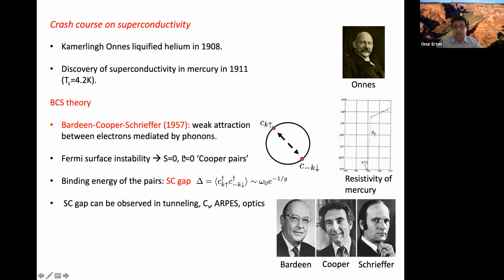And if you have these L equal to 0 S-wave superconductors, the superconducting gap forms a clean gap. This would be like an S-wave superconductor. So this clean gap can be seen in all these experiments. Mainly you no longer have low energy fermionic excitations, and the fermionic excitations come from breaking these Cooper pairs, and then you create electron- and hole-like excitations. So this is one of the characteristics of superconductors that can be experimentally seen.